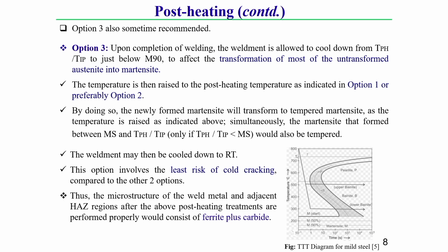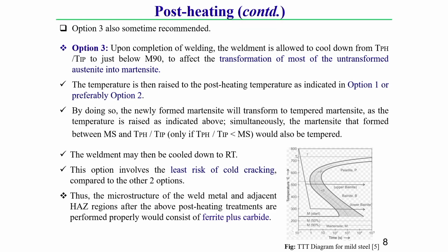Then, from this below-M90 temperature, we heat it. After heating, this heating temperature can follow option 1 or option 2. Generally here we use option 2: after the martensitic 90% transformation range, we heat the welded specimen to around 600 to 750 degree centigrade and hold for around 2 to 4 hours. After that, we cool down to room temperature slowly and steadily. This is called option 3.